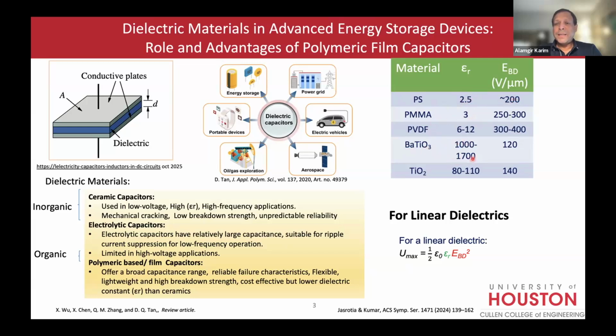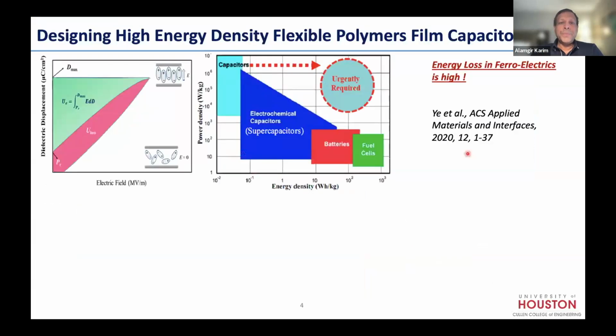But take barium titanate, a ceramic: it has high dielectric constant, low breakdown voltage. So really, no single material has the combination of high permittivity and high breakdown. Ideally, you want to make a marriage of the two, meaning a hybrid material, a hybrid polymer capacitor, to capture these properties. If you look at this plot, this is called the Ragone plot, power density versus energy density. Capacitors are here.